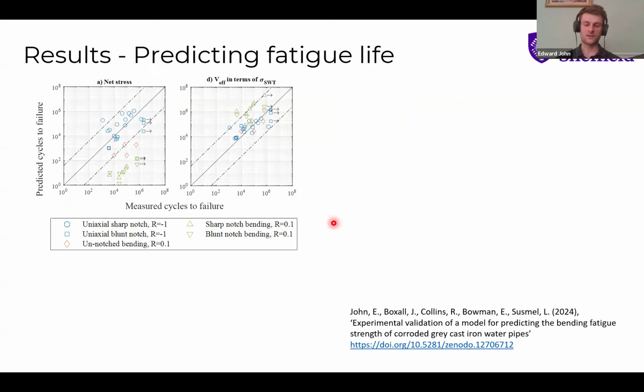So the next thing we set out to do is basically trying to figure out, can we predict this behavior? So we've seen that in some cases the depth of the pit is not enough to tell us how damaging it is. So are there models that exist that we can use to predict this behavior? So we tried out quite a few different models, but I'm just showing the results of two here. So these basically show prediction plots. So along the bottom, we've got the measured cycles to failure from the experiments, and then on the left axis, we've got the model predictions.